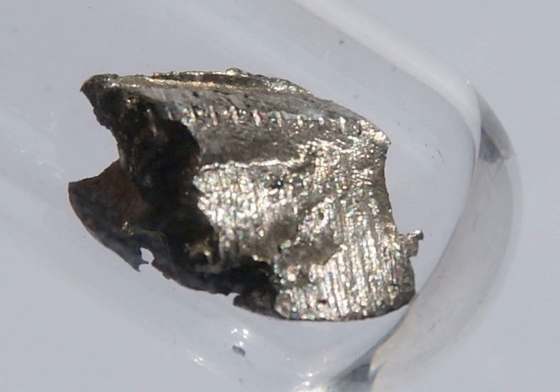Ceria is the most widely used compound of cerium. The main application of ceria is as a polishing compound, for example in chemical mechanical planarization (CMP). In this application, ceria has replaced other metal oxides for the production of high-quality optical surfaces. Major automotive applications for the lower sesquioxide are as a catalytic converter for the oxidation of CO and NOx emissions in the exhaust gases from motor vehicles. Ceria has also been used as a substitute for its radioactive congener thoria, for example in the manufacture of electrodes used in gas tungsten arc welding, where ceria as an alloying element improves arc stability and ease of starting while decreasing burn-off. Cerium IV sulfate is used as an oxidizing agent in quantitative analysis.